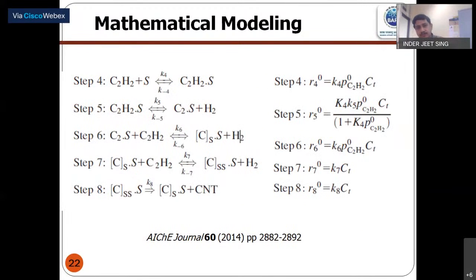Now if I can have some mathematical model for these steps, like acetylene is reacting with S, meaning a site, and it is adsorbed on the site. Then after adsorption, it can break into carbon molecules, C2, and hydrogen can come out. This carbon molecule once again reacts with the incoming acetylene and gets saturated, hydrogen comes out, and again the saturated one can react with the acetylene and become supersaturated, and finally the supersaturated one can form CNT and come back to the saturated state. So only the last step is irreversible, all other steps are reversible.